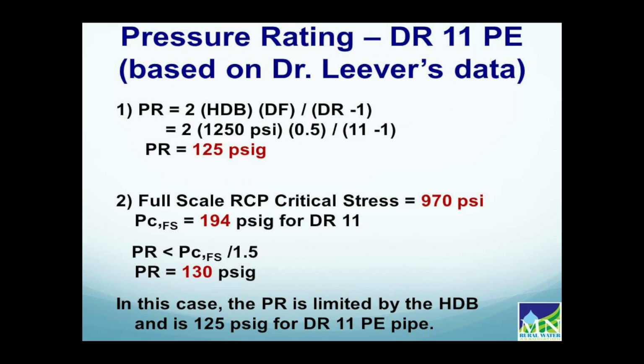Taking a look at this example, this was DR11 polyethylene that was tested. According to the pressure equation, it would have a pressure rating of 125 psig. Looking at its full-scale critical pressure and dividing by 1.5, it would have a pressure rating of 130. We used the lower of the two values to be more conservative. In this case, the standard pressure rating from the HDB is lower, so that would be the pressure rating for the pipe.